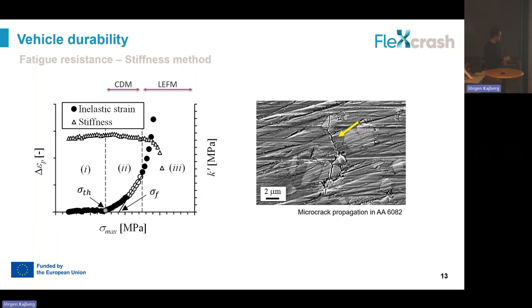So by doing that, we obtain this curve. And we can clearly identify the different regimes. So no damage, these first stages of damage related to micro crack initiation and propagation, and finally, this macro crack propagation in the material. Here you can see these micro cracks in this regime 2, and we are using these points to assess the